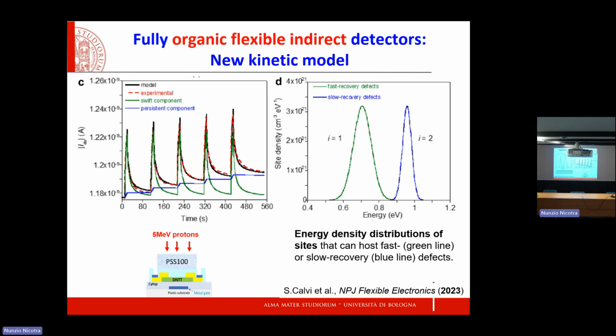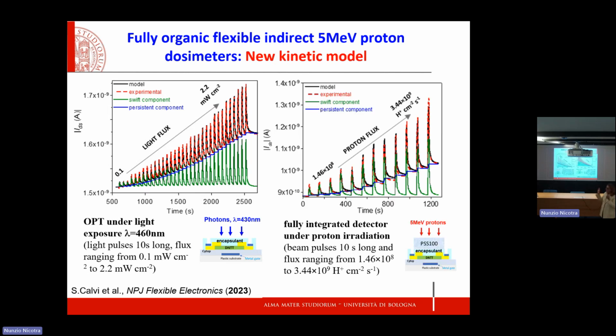The final message is that by using these two distributions of traps, we can model very nicely the response. The response is the red dotted line. So keep your eyes on the red dotted line that provides a sort of baseline increase. And then we have these two components, the swift fast component, which is the green one associated to this trapping state, and the blue persistent component associated to the slow component. And if we put these two in the model that I showed you before, we can nicely reproduce in black and model the response of the device. So the message is we get exactly the same response, photons onto the phototransistor and protons on the full device. So definitely this is due to the organic phototransistor, and there is no damage of the phototransistor.